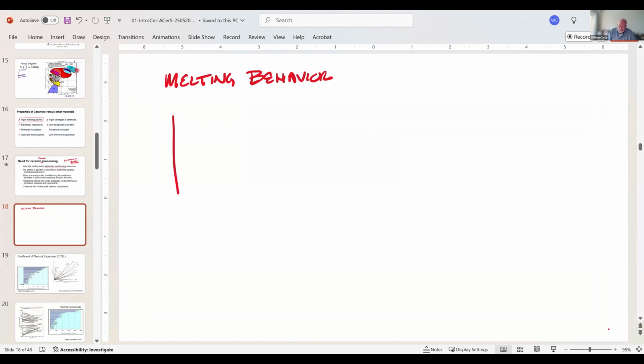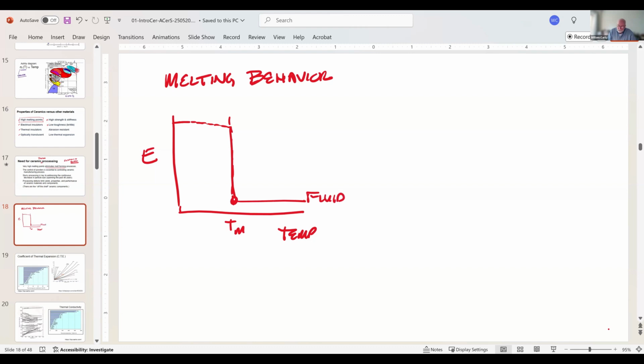What you typically see is that if you looked at, say, temperature versus elasticity, it would come across to be very, very elastic. It might have some small decrease in elasticity as it approaches the melting point. And when it hits the melting point, T sub m, it drops precipitously and becomes a fluid. Very, very low elasticity. A glass, by comparison, and I'm going to use a different term here, I'll use viscosity, which we typically denote with an eta symbol, versus temperature. The curve now does this.